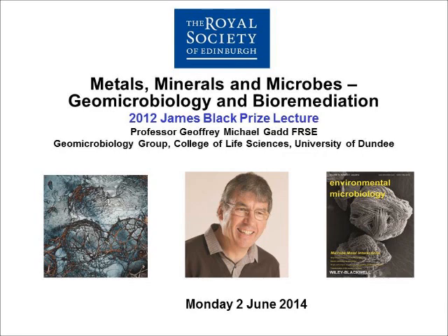And apologies, old-fashioned data, I tried not to, but anyway, you can see the pH fall as the leachate comes and the sulfate stabilizes. There's an example of leaching from an actual contaminated soil that we obtained that contained those kind of metals, and you can see cobalt and nickel were actually in this soil. You can see quite efficient leaching efficiency of these organisms. Cobalt 74%, copper 69, manganese and nickel 68, for example.